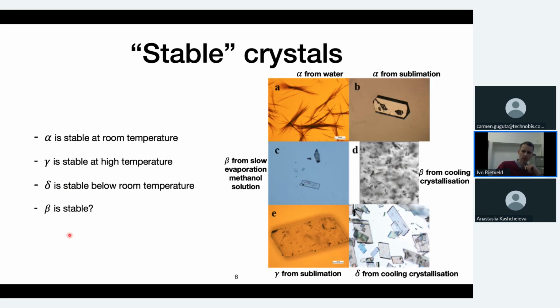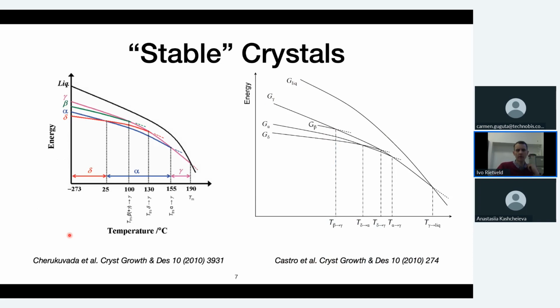The question that was, in a sense, still asked, and for that, I show two energy temperature diagrams here that were known in the time that we started with this research, which was in about 2017. Two papers that I suppose slightly by accident got published roughly around the same time. A few things that are interesting here are, as you can see, the transition that was listed for the alpha to gamma transition is about 155 degrees Celsius. Then you can see that alpha is stable down to room temperature, and after that, delta is supposed to be the stable form all the way down to 0 Kelvin, is the idea.